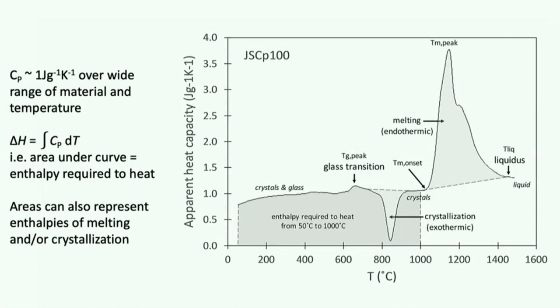Right, so what's going on? So the actual heat capacity of our starting material is this. The glassy part goes through the glass transition right here. There's a little jump. It's the configurational heat capacity. As you keep heating, that now supercooled liquid realizes it should be crystallizing. And I do anthropomorphize my samples much more than I should. But anyway, it crystallizes. That is exothermic. And then we melt it.